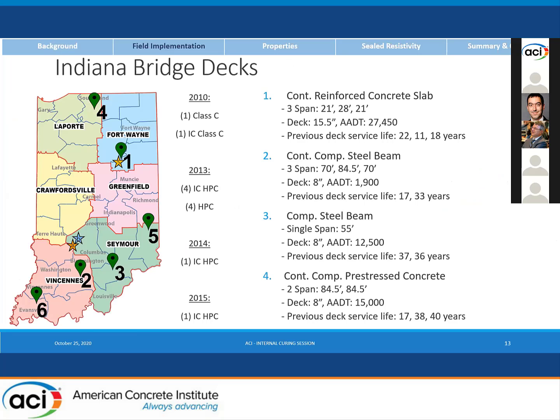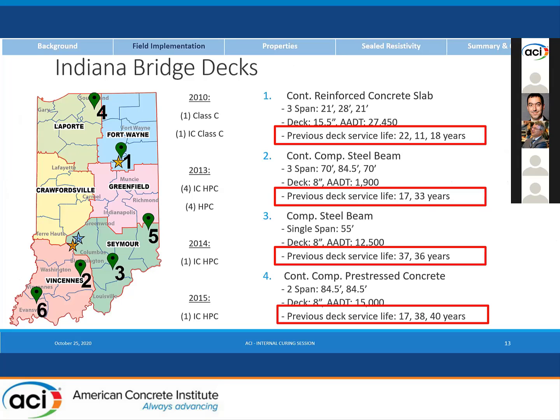For the bridge decks in Indiana, there were originally 4 as a part of the study. There was a couple added after the fact. I won't dwell on this. There's a full report that I would love if everybody would go read. But what I do want to draw your attention to is the actual in-service life of the previous decks, and you can see that indeed all of them lasted anywhere between 11 and, the best was, 40 years. So it is indeed a problem.